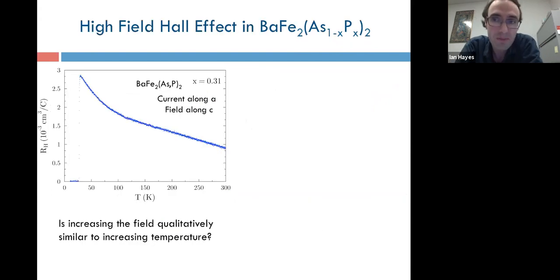So start with optimal doping. This is the Hall coefficient at low fields for optimally doped barium-122, 31% phosphorus substituted. And I should start by saying that for all the data I will show you, the current is passed along the a-axis, and field was applied along the c-axis. That'll be the same configuration for all this data. Now, looking at the temperature dependence here, there's temperature dependence all the way up to 300 Kelvin, but especially at low temperatures, you start to see a sharp upturn that is reminiscent of what I just showed you in the cuprates and in some heavy fermion compounds.